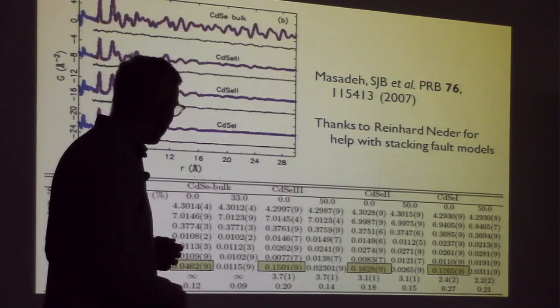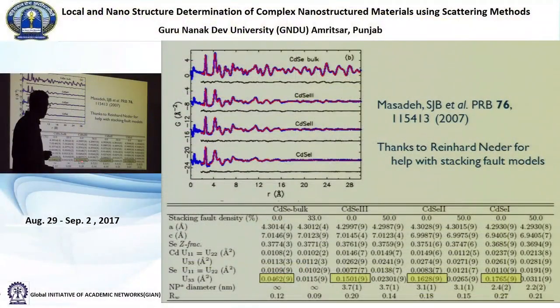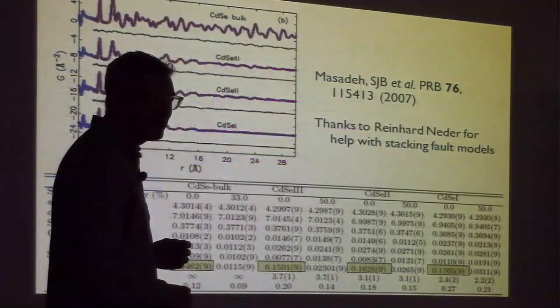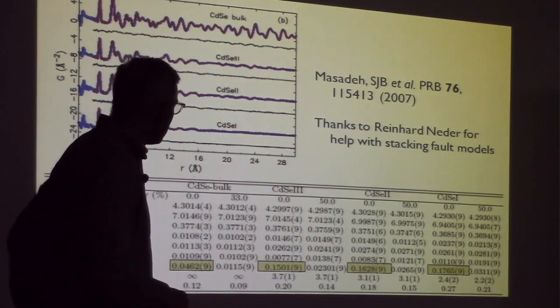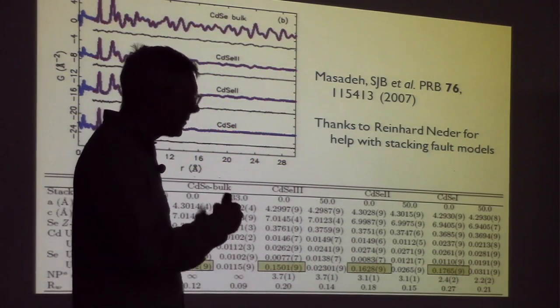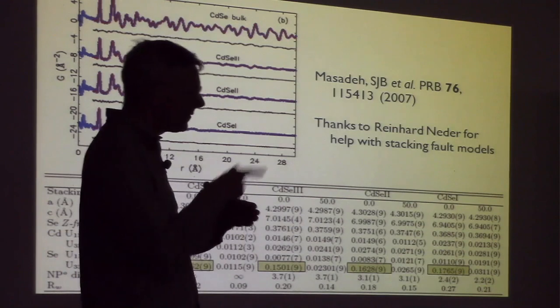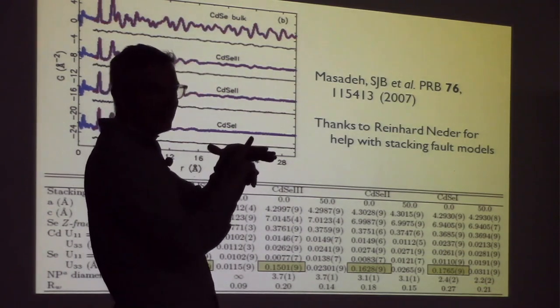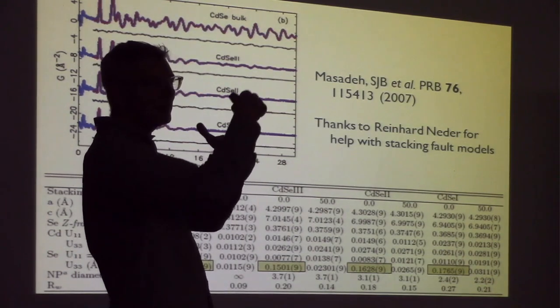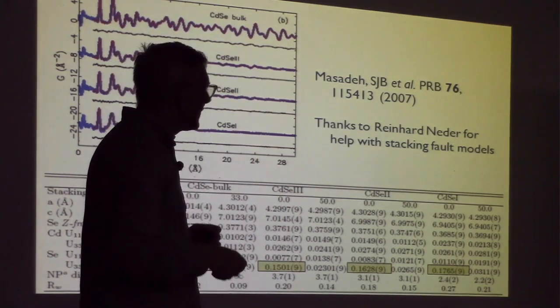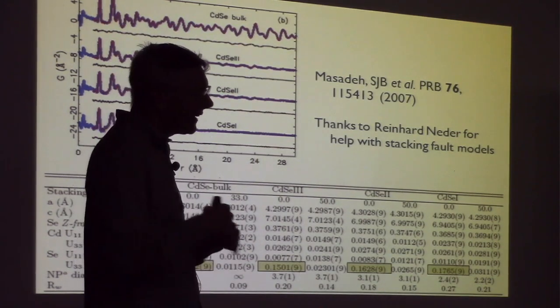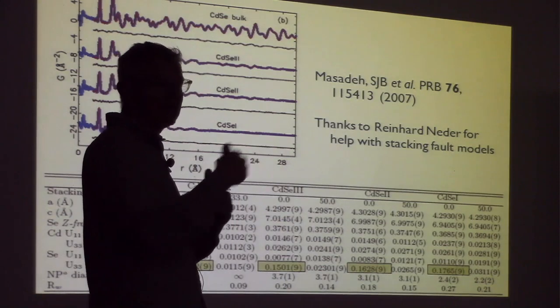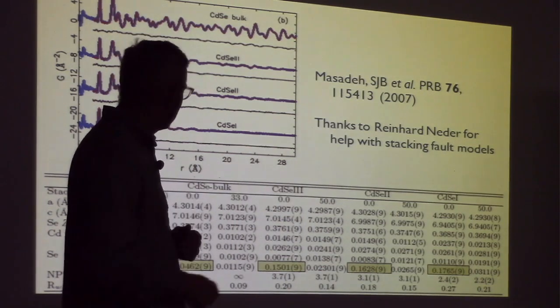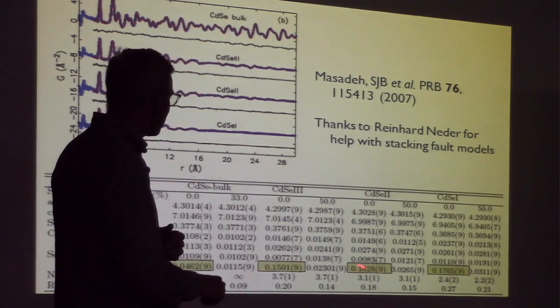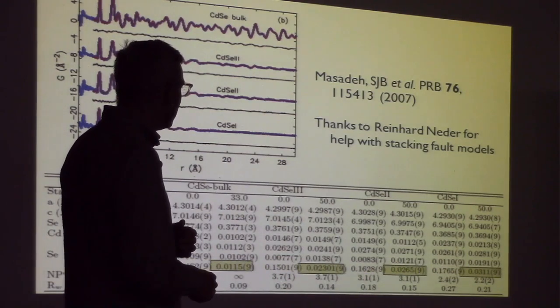And so what's actually happening here is that these materials are heavily faulted. They have a large number of stacking faults. And when you have these stacking faults, then your crystal structure model is looking for an atom in a certain place along the C direction. It can't find it because of that stacking fault. And so what it does is it tries to remove the intensity from the pattern that comes from that correlation. And it does it by increasing this. So this is unphysical.